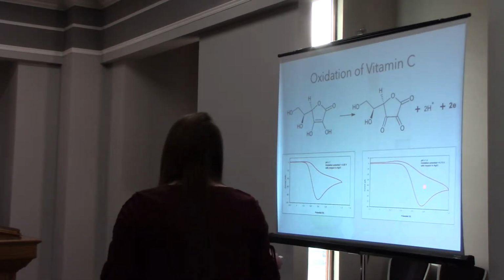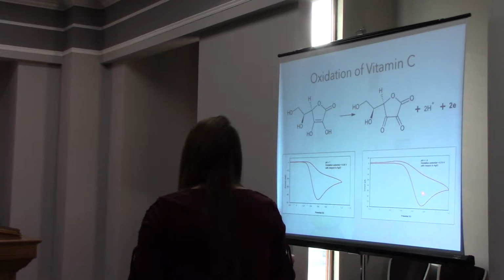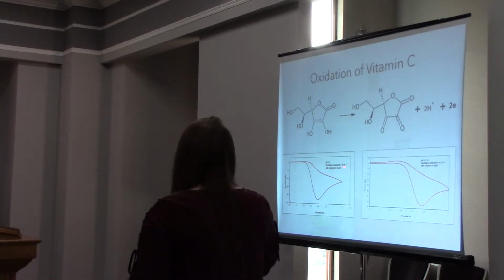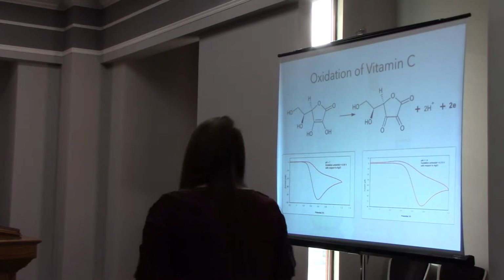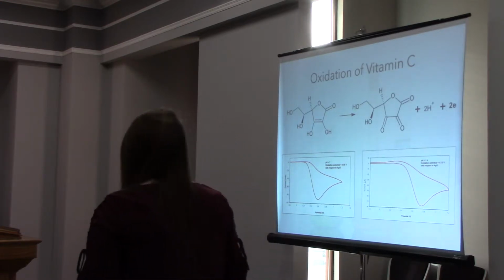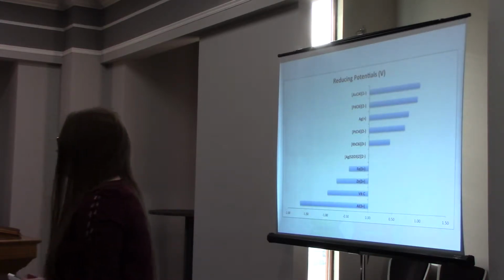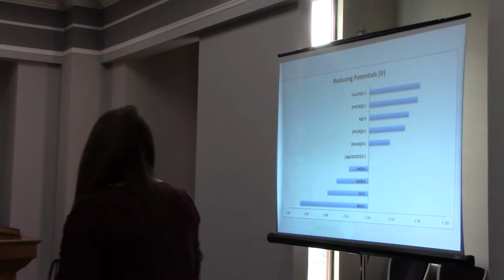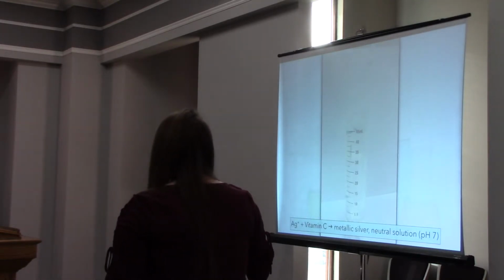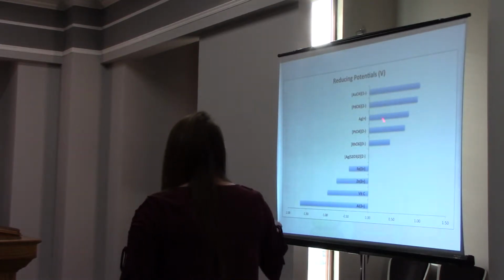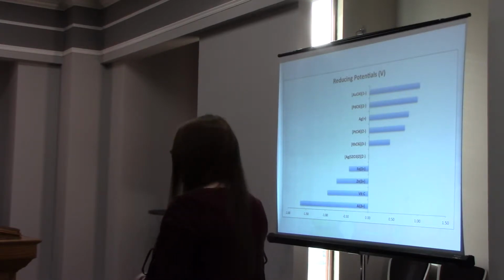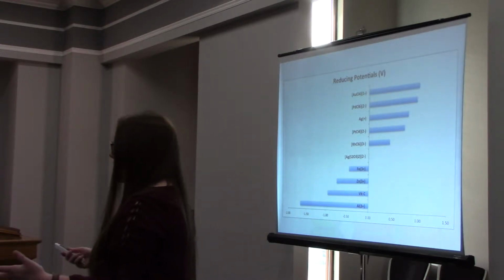We found that with a lower pH, it had a higher oxidation potential. So with a pH of 7, it had an oxidation potential of 0.6 volts, and then with a pH of 1.4, it had an oxidation potential of about 0.73 volts. And this is important because when you are trying to reduce the metals out of these species of metal ions that have positive reducing potentials, you need something with a negative reducing potential. And so you can have a greater reducing potential if you have a lower pH vitamin C.